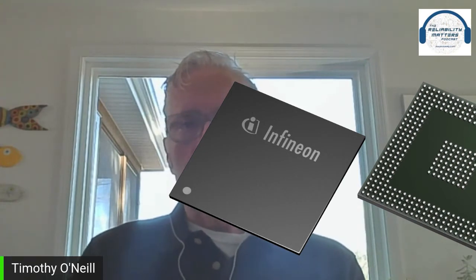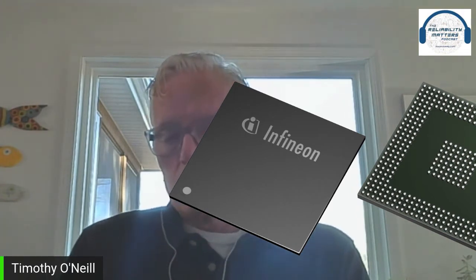Thanks, Mike. There are three fundamental types of voiding. The first type occurs on ball grid array packages, or BGAs. When the BGA is reflowed with solder paste, the outgassing products of the solder paste are trapped within the sphere of the BGA interconnect and create what's known as a void. The IPC specification on the largest void that you can have is 30%, and it's 30% cumulative, not an individual void of 30%. It's 30% adding all the voiding together on the BGA. A lot of the X-ray equipment out there today is sophisticated enough to do that calculation for you.